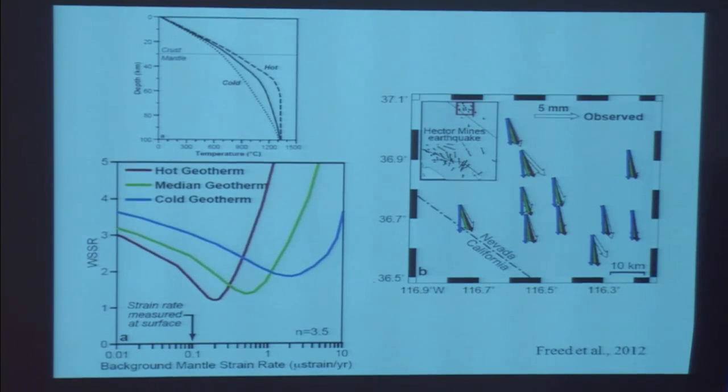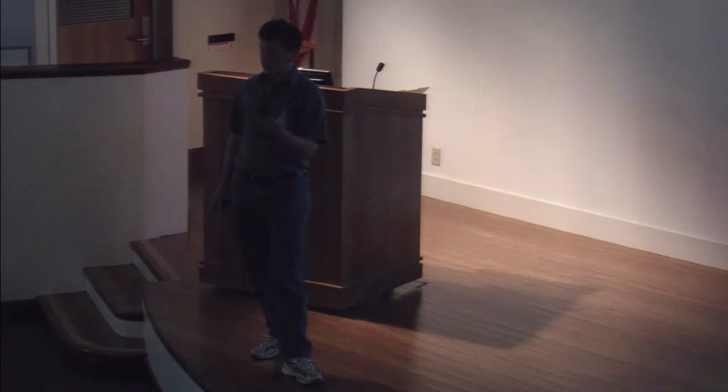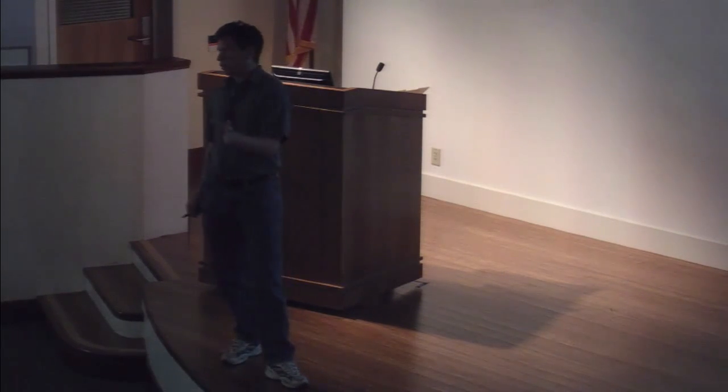let's just recap. Nonlinear creep is nonlinear because of this dislocation density stuff. It imparts a lattice preferred orientation, which we can see both by looking at rocks and by looking at seismic anisotropy. We know about a mechanism that can occur at lower stresses because we can excite it in the laboratory, because we can cheat by making really, really fine grain rocks. When we look at natural rocks from higher temperatures, we see the lattice preferred orientation evolution the same as in the lab, and we see evidence even from larger scale things like post-seismic creep, or even larger scale things like lithospheric scale instabilities, that you have a dislocation creep mechanism near the lithosphere-asthenosphere boundary.